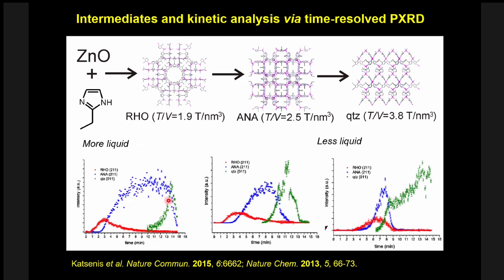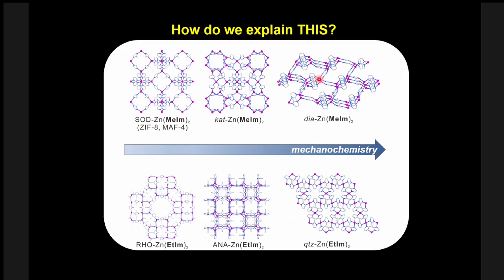So here are some really early kinetic curves of how the reaction profile changes when you mill with the addition of a liquid or less liquid or more liquid. And in making these ZIFs, you can see that you take your metal oxide, you take your imidazole reactant, and when you mill them, you don't go straight to this framework which has a topology, the structure of quartz, QTZ, but actually it appears through a series of intermediate phases. So we are now starting to see these complex reaction mechanisms, and we are thinking about how does this work? Why do they form? And really the first question was, how do we explain this?